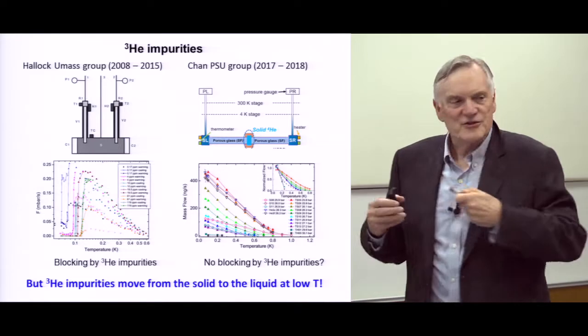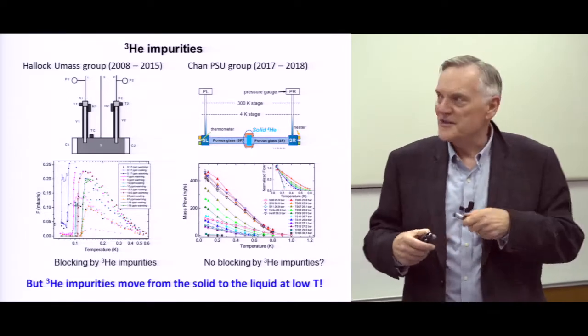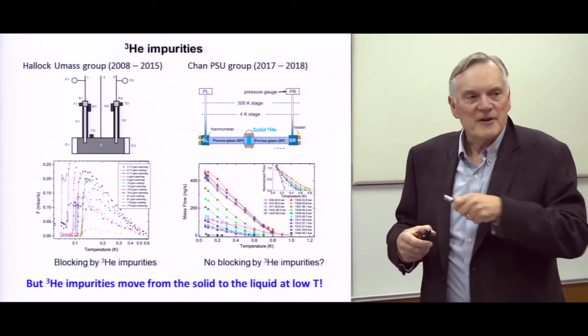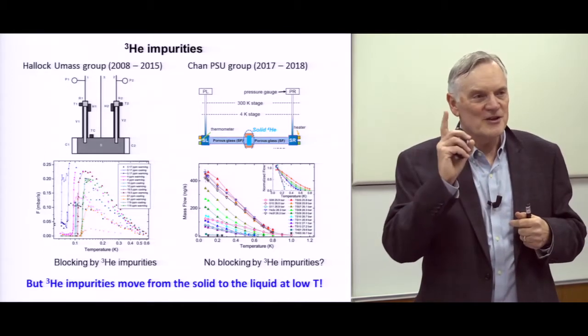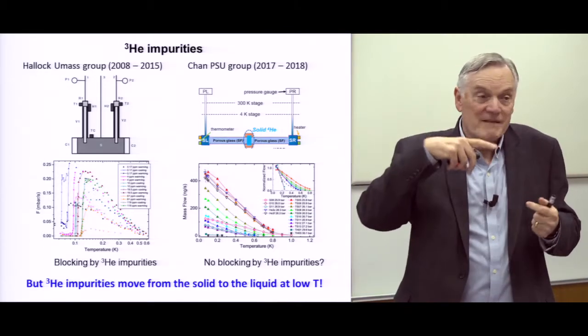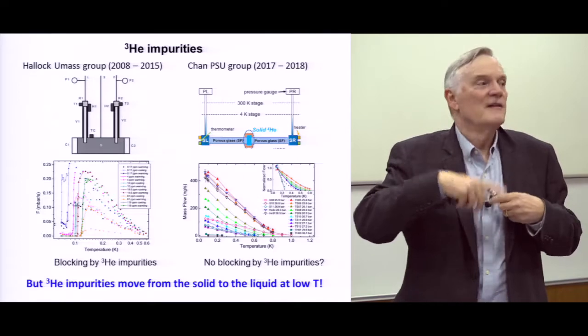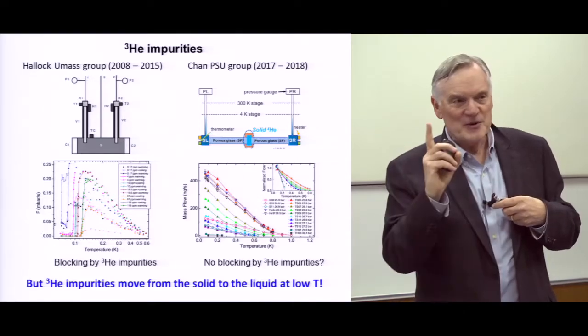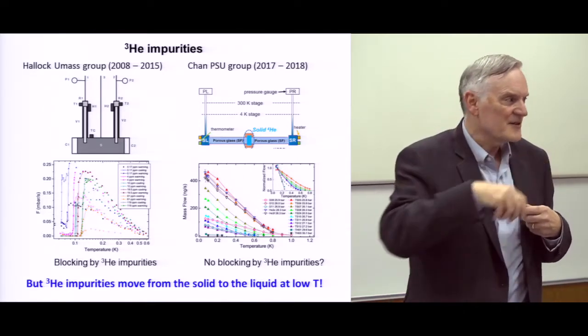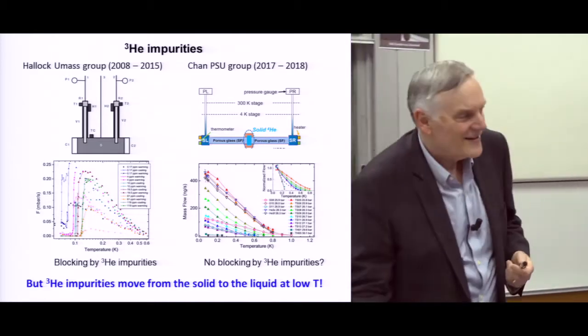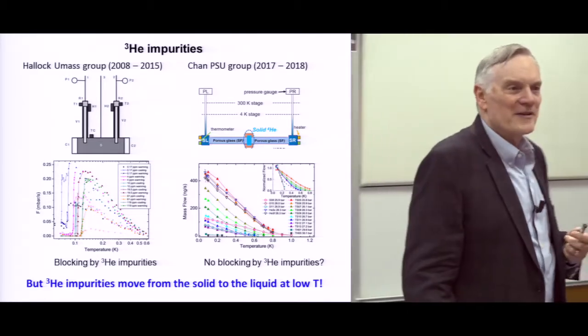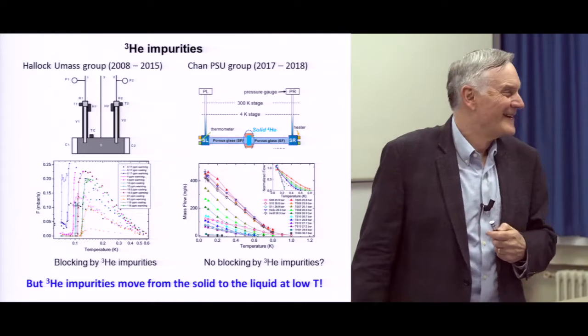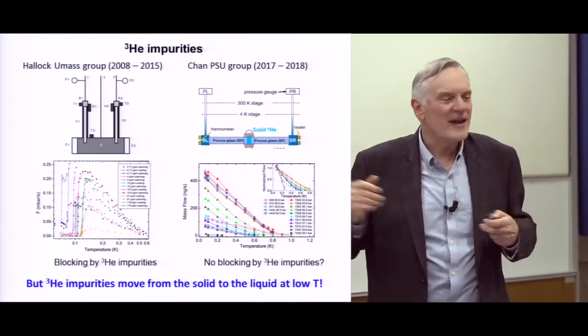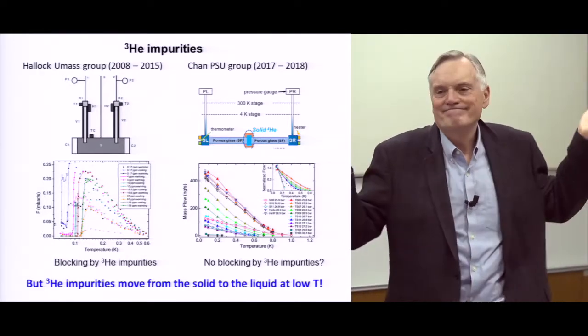The thing they did, which may or may not mean anything, is they inserted little bits of graphite in here to try to force the crystal to grow this way and this way. There's no direct evidence that it worked, but if it worked, they saw a difference between the C-axis this way and the C-axis in the flow direction. But I confess it's more like a hope than it is a proof. But they're working hard to try to pin that down. I can't think of a perfect way to do it except, who knows?